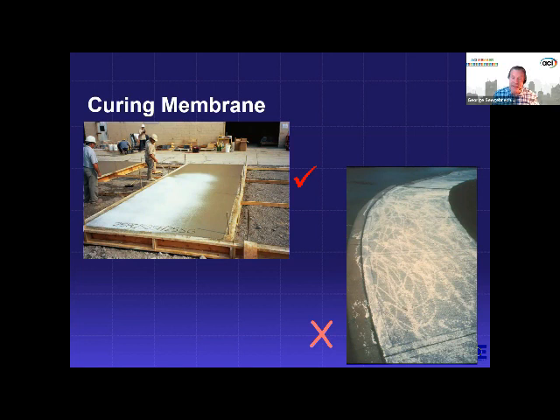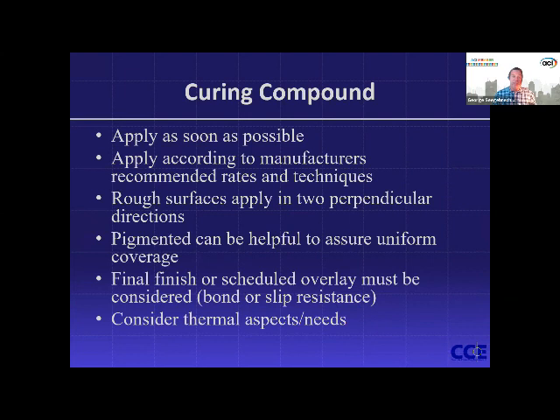And when I got rotated to curing compound, number one, spray it downwind. I got a face full of that, so my face stayed hydrated. But keep the nozzle clean too. And one of the best ways is just to keep it going. That's enough said. So apply that as soon as you possibly can. If you have, say, a rough wood-formed or scratched shotcrete surface, you'll have to apply it probably in higher dosages even than recommended. And most say to apply it in 2 perpendicular directions.